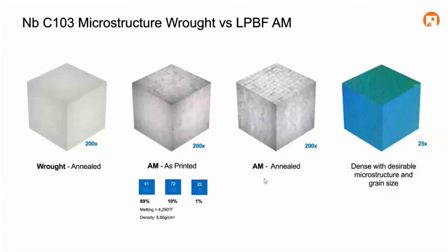And if you're not as familiar with niobium C103, you can kind of see the alloy composition here - about 10% hafnium and 1% titanium. Whereas the nickel superalloys we're talking about melting temperatures of the 3000s, we're talking melting temperatures for niobium-based alloys in the 4000 degree plus Fahrenheit range, while also still having a density that's pretty similar to those of other nickel-based superalloys. So not a huge weight debit from something like this.